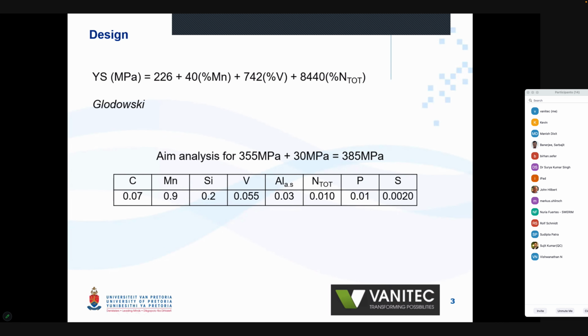We started off using Bob Glodowski's empirical formula for yield strength that he collected over the years, shown over there. It's proved to be fairly reliable, where you can predict yield strength as a function of simply manganese, vanadium, and total nitrogen content. We were aiming for a yield strength of 385 MPa, which is 30 megapascals above the minimum spec. So this would typically give us a typical composition as shown below.